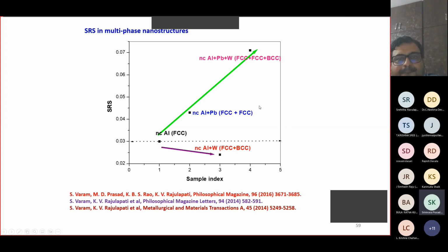So the strain rate sensitivity value is 0.0084. That's very low. That means these materials are not strain rate sensitive at these microstructural features. And the activation volume is about 13 b cubed, b is the Burgers vector. That's also pretty low. And this we have discussed before. Again, you have a multi-phase structure here, FCC plus B2, and it has nanostructural and microstructural features, but the SRS and the activation volume follow the formulations that were exhibited by the simple nanocrystalline materials that we have seen before.